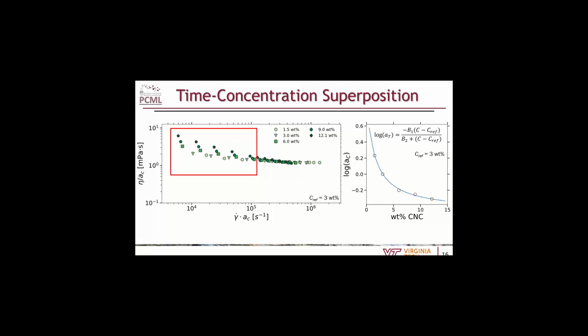That being said, we can still make a pretty decent looking shift factor plot using the Williams-Landel-Ferry version of the time temperature superposition equation, just swapping out the temperature terms for the concentration terms labeled C and Cref in the top right corner. We did this all for a reference of 3 weight percent CNC in water at room temperature, so 25 Celsius.